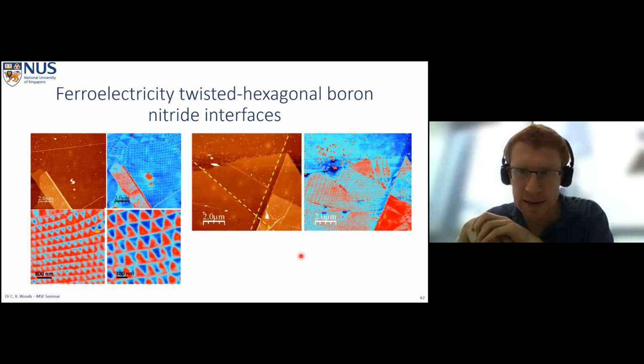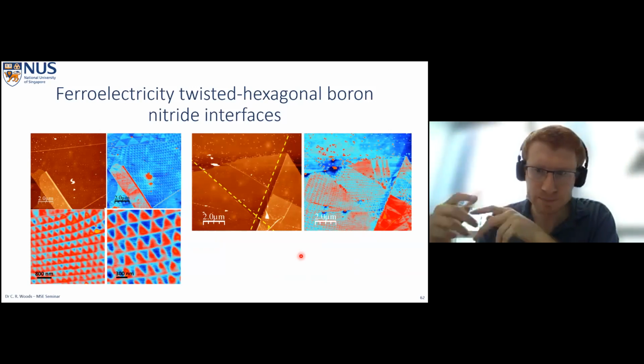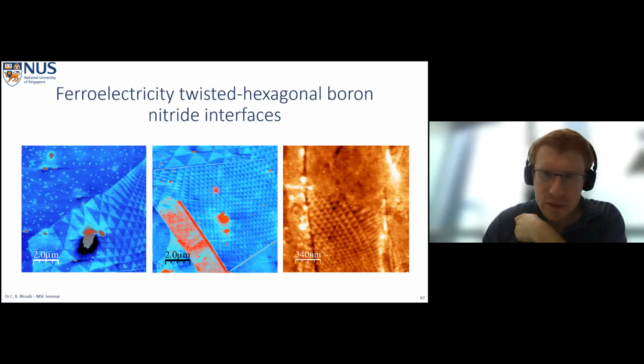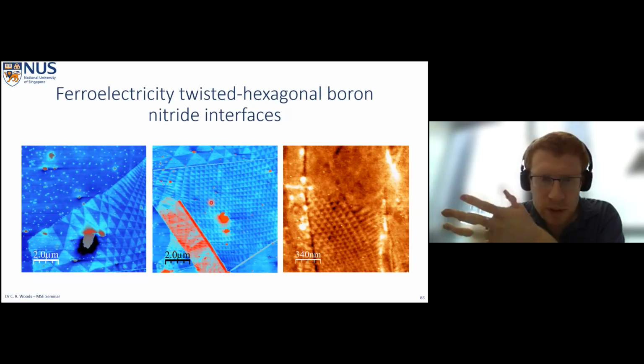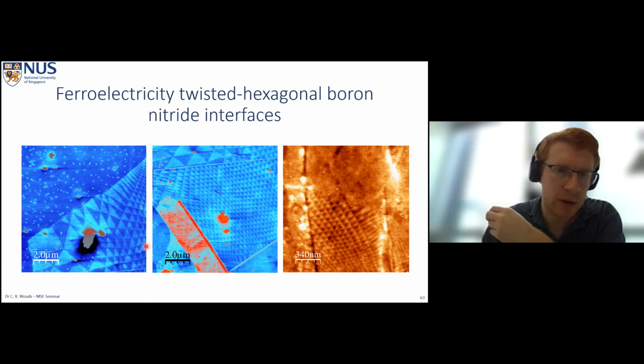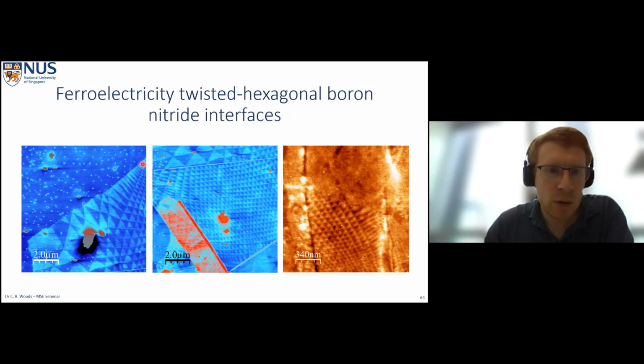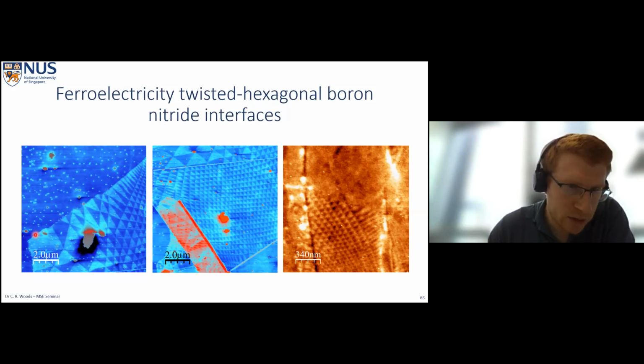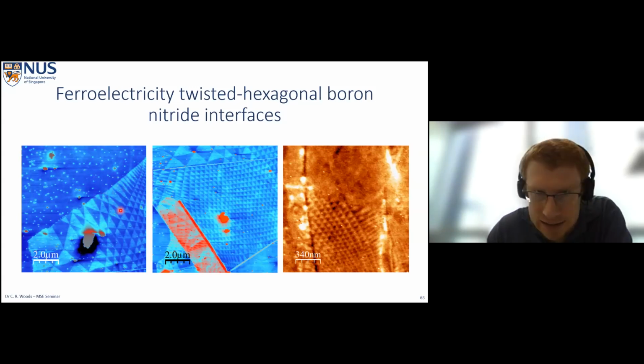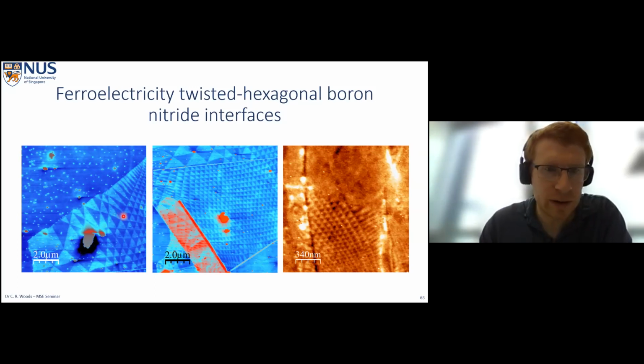And so when we produce lots of samples like this, we see a lot more of these hexagonal-like domains. And they have different sizes, which really just relates to the exact alignment between the hexagonal boron nitride crystals. But if you look here, we've got 2 microns. So we're getting triangular domains, a triangular superlattice with 2 micron-sized domains. So this is really quite nice images. One thing I like about this image is that you can see exactly where the top boron nitride ends, and that we see that the EFM signal becomes perfectly uniform when we move off of the top boron nitride. And so this tells us that this signal is exactly related to the interface between our 2 boron nitride crystals, and not some other feature within the boron nitride that we would need to understand.